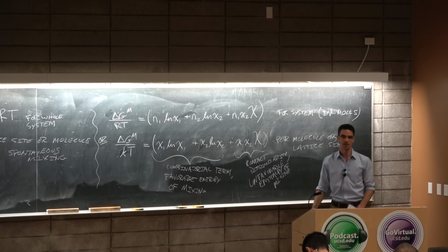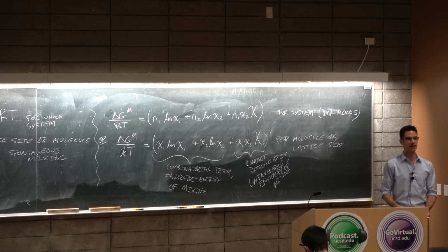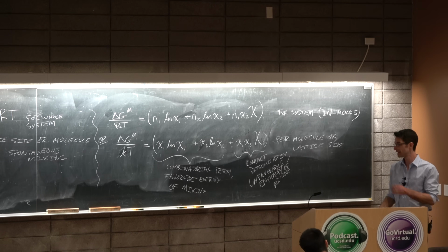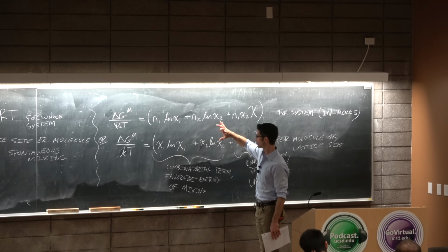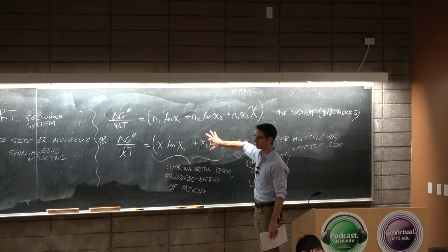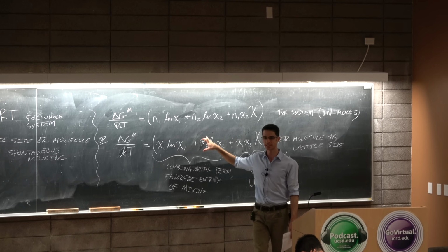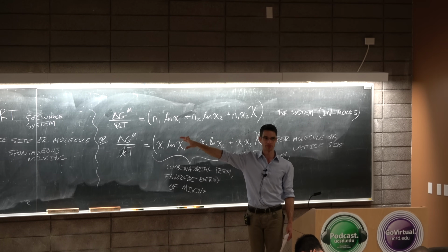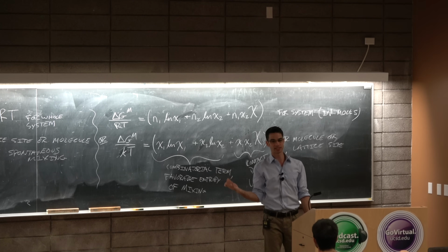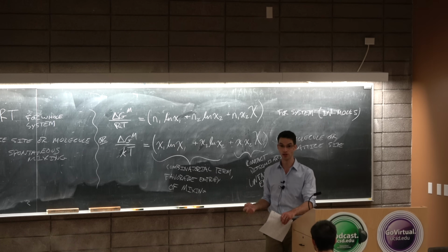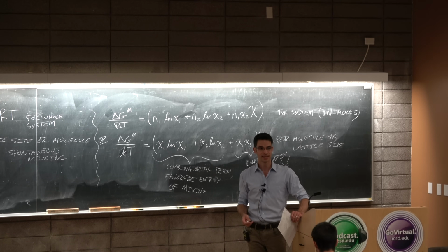So the key result we will arrive at on Wednesday is the fact that if component 2 is a polymer, we saw based on the Flory Huggins entropy of mixing, the entropy of mixing associated with 2 is very low for high molecular weights.